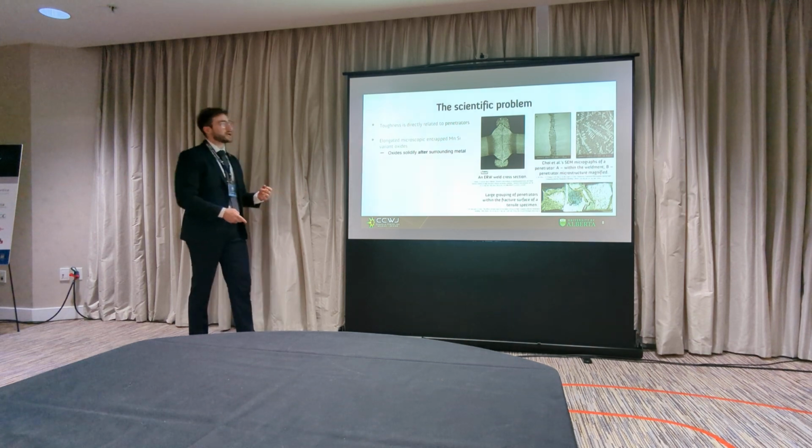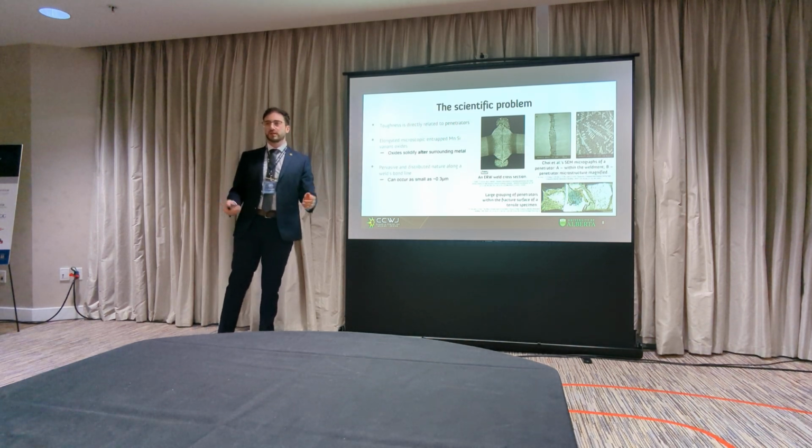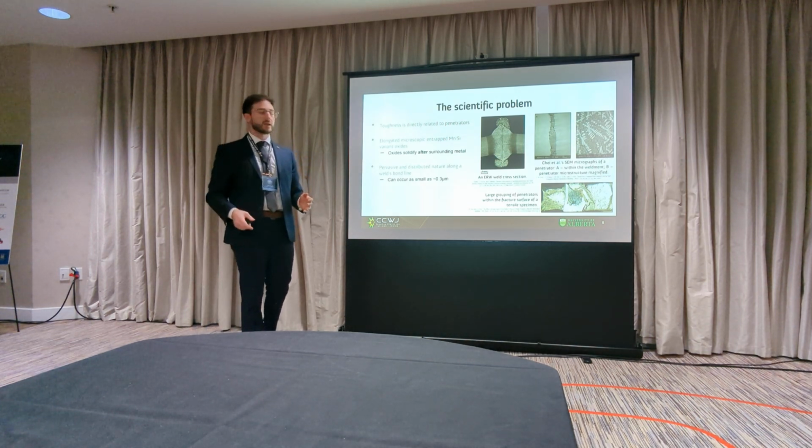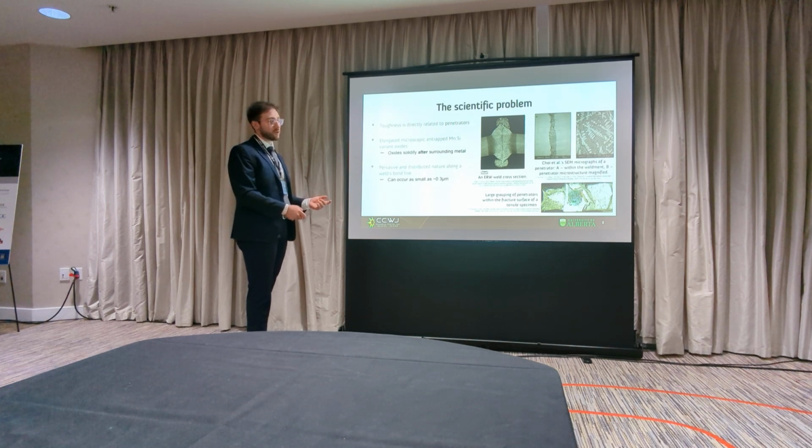Because they have a pervasive and distributed nature along the bond plane, like I mentioned here, they can facilitate fracture very easily because we have them all in one plane. Cracks can go through like nothing. And there's an example of a ductile Charpy test. You can see a grouping of penetrators here that have a local cleavage plane here.